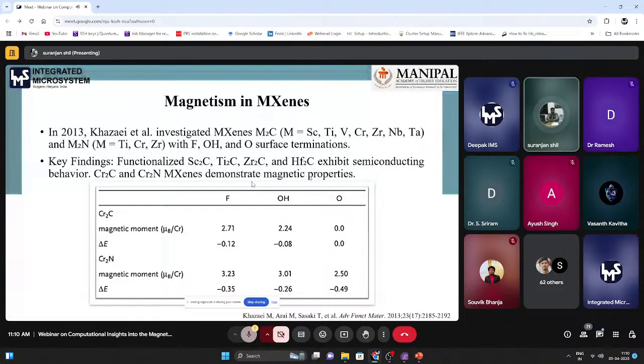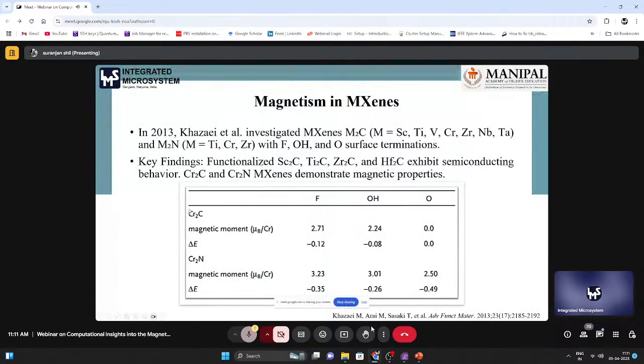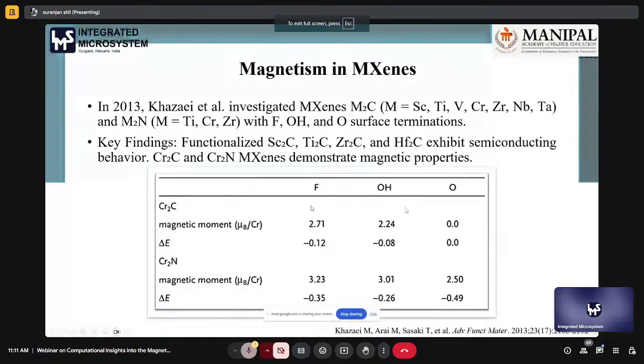They have lots of properties, and are used for solar cells and batteries, many things. But we are especially interested in the magnetic properties, which are not so common in MXenes. There is a report in 2013 by Khazaei's group, who investigated MXenes with metal carbides, with scandium, titanium, vanadium, chromium, zirconium, niobium, and tantalum, and M2N with titanium, chromium, and zirconium, with fluorine, hydroxyl, and oxygen surface termination. In the tables, for chromium carbide, they found a magnetic moment of 2.71 Bohr magneton with fluorine termination, and with hydroxyl termination they got 2.24, but with oxygen termination they got non-magnetic behavior.